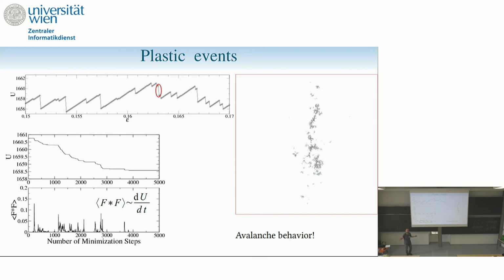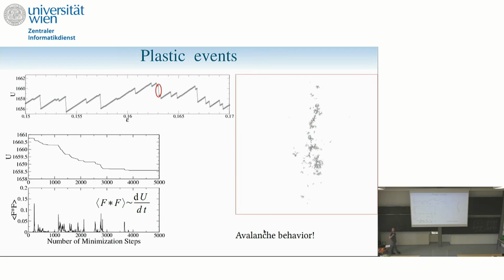The statistics of the result don't depend on it. We have done that with lots of methods, and people have done that using different methods. What you see systematically, here in a large system, is that the points correspond to places where you see a significant rearrangement. We measure that by some fluctuation of the local, maybe the D2min criterion for those who know.